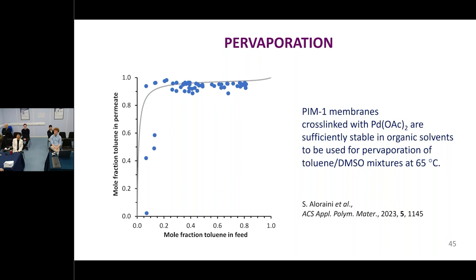The trouble is, there are many ways of cross-linking. We also lose free volume. But we have shown with this palladium acetate method, we can create membranes which are stable enough to be used for pervaporation of toluene and dimethyl sulfoxide, for example. And this is where there's a big volatility difference. In fact, we can pull pretty much almost pure toluene out of the mixture, and that's of interest in terms of the way in which aromatic hydrocarbons are produced, in trying to improve some of the processes.